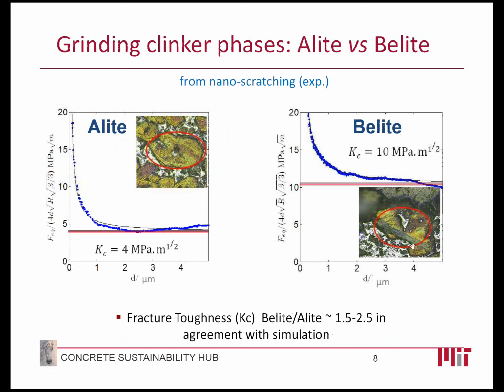Okay, this is the actual measurement. Because we are not only doing simulation or calculations, we are also developing experimental methods. This is a new method called nano-scratching. It is a way to probe a very important property of those crystals, which is the fracture toughness, and that relates to grinding at the end of the day. You can see that the value given for alite is about 4, in units of megapascal square root of meter, while for belite it is about 10. So the ratio of belite over alite for the fracture toughness is roughly 2, which is in agreement with simulation. It tells you that belite is tougher than alite and therefore more difficult to grind. Next slide, please.